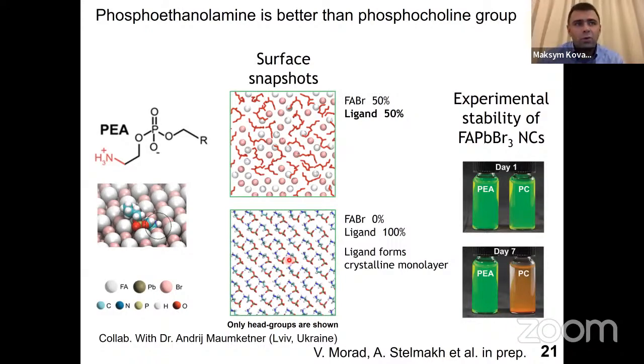So what experiments have shown is that indeed, if you take exactly the same organic rest here and just compare the primary ammonium group with the phosphocholine group, like shown here, on day one these colloidal solutions will look similar, but a few days later you'll notice a big difference, because the primary ammonium-based ligand desorbs much slower than the one which is phosphocholine-based. Basically, in good agreement also with the simulations showing this much more stable binding.